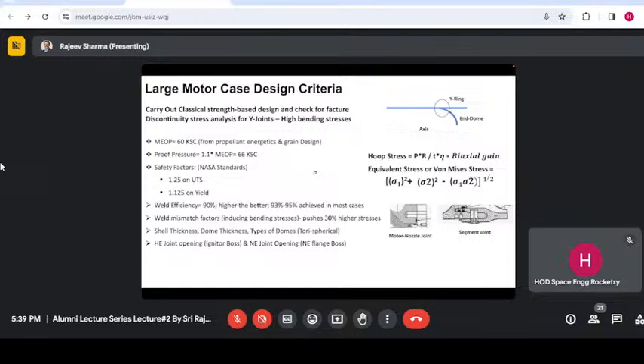It did not. So then we started polishing the plates for the domes to a lower thickness, because the thickness of the sheets and plates was standardized. We would get a particular thickness for the whole system for economies of scale. Then the sheets for the domes were identified and we would polish them to a lower thickness before they were actually used for making the tori-spherical domes. And this also added cost. This added fabrication time. And remember, time to market was important. So every day, Dr. Agarwal was asking me, what is going on? When is the first rocket ready for burst test?